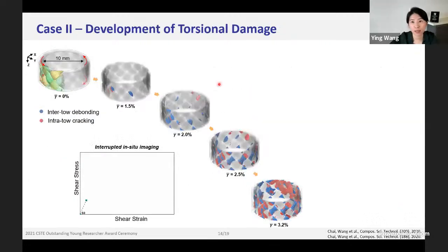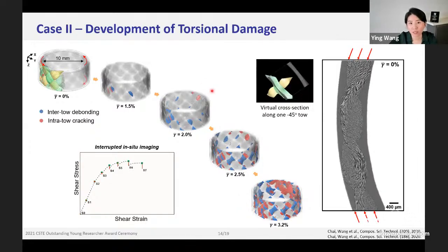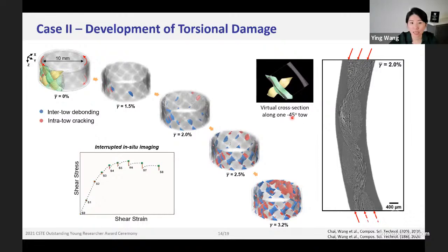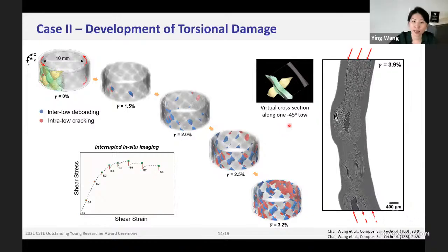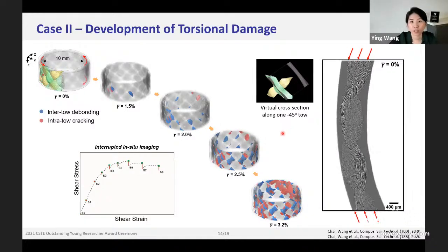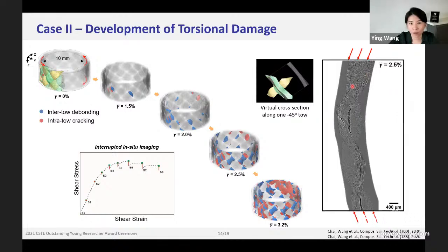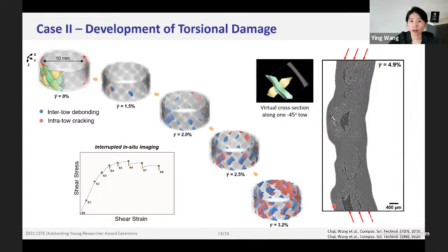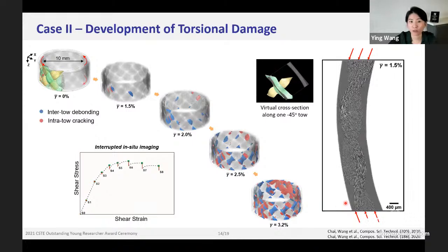And here shows the 3-dimensional damage evolution in the braided composite tubes. The inter-tow debonding and intra-tow cracking damage has been highlighted in different colors in 3D. Also, X-ray CT offers us the capability to virtually section any plane that we are interested in without damaging the sample. In our case, we are interested in the planes parallel to the fiber direction. And here shows a cross-section along the -45-degree tow. It's interesting for us to find that in the torsional failure, the compression failure, fiber microbuckling and kink band formation in the compressed tows is also the critical damage mode leading to fracture in this material.